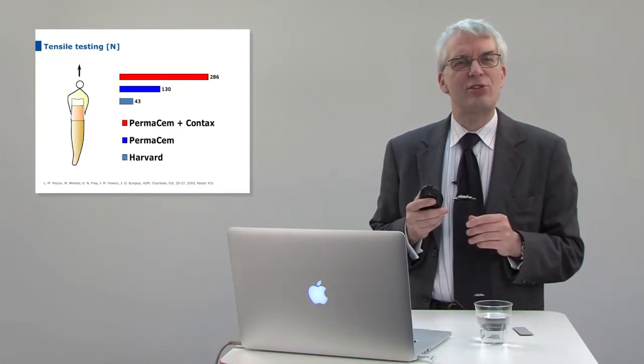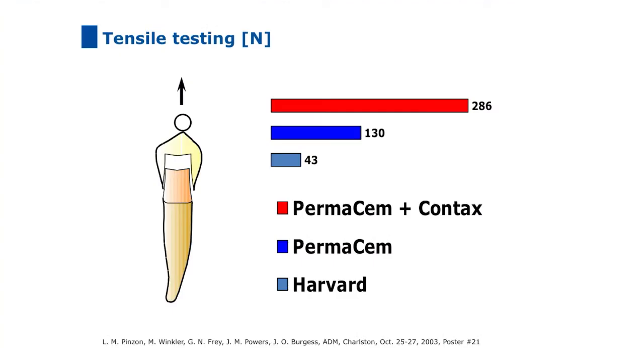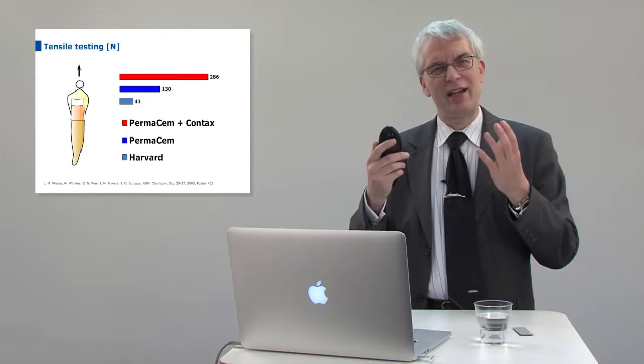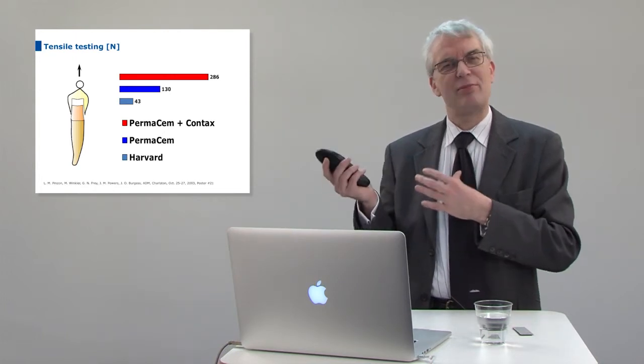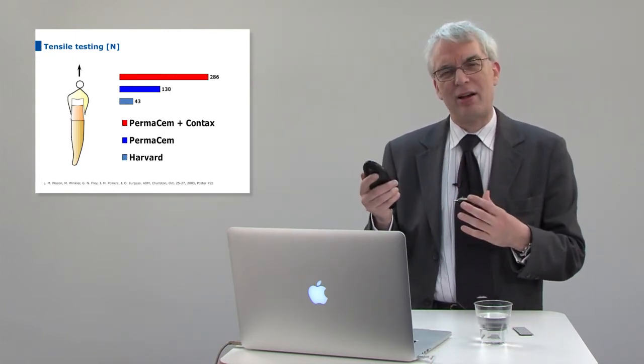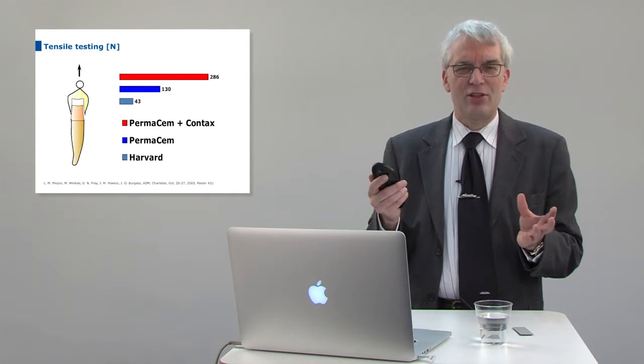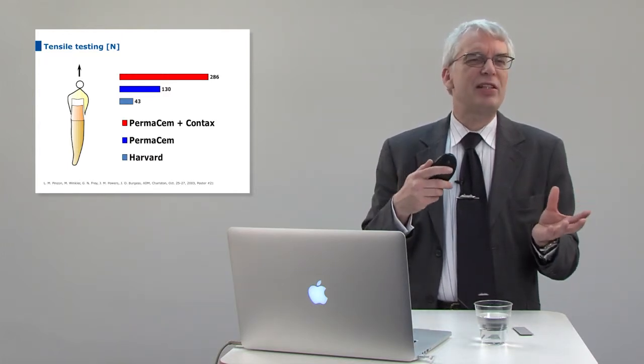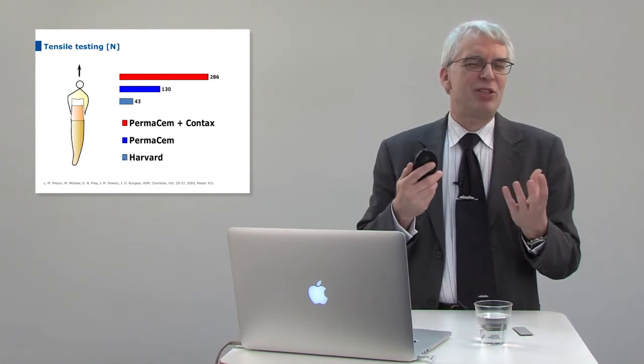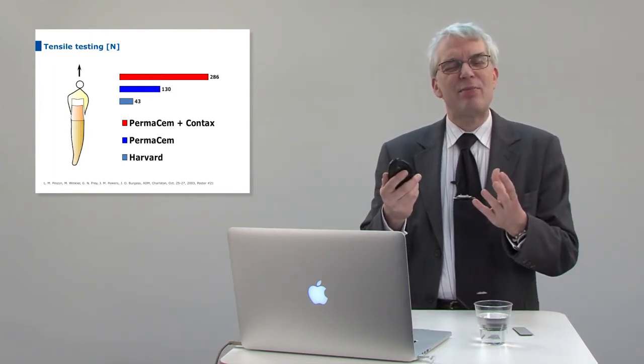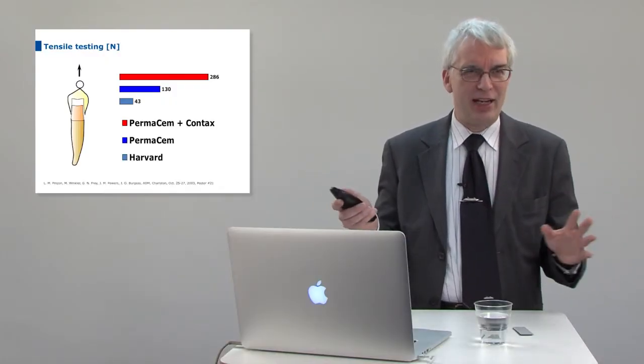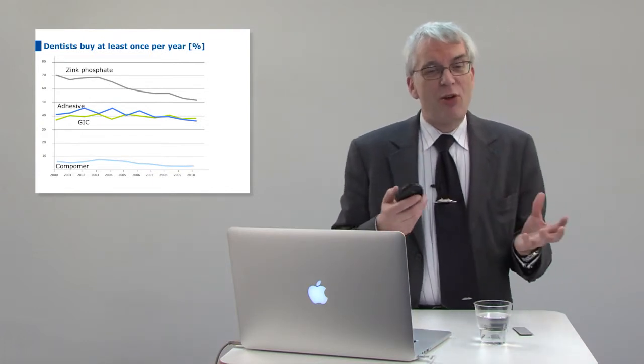And the results were quite striking and stunning. First of all, even without a bonding agent, Permacem had 3 times as much adhesion to the tooth structure as did Harvard cement. And the second part, you could even double this figure by using a bonding agent. So this sounds good, but for a lot of dentists it was also very frustrating because they always wanted to know, do I need a bonding agent or don't I, and when? And this is now all over because with Permacem 2.0 you don't need any bonding agent. And this is what really got dentists to it.